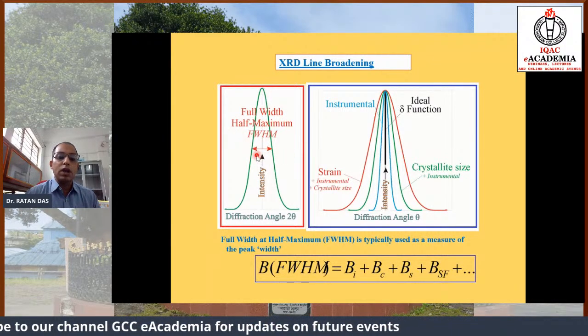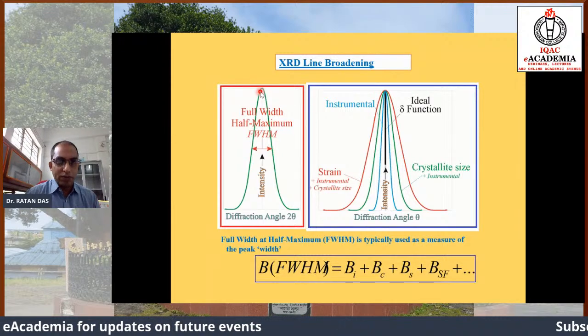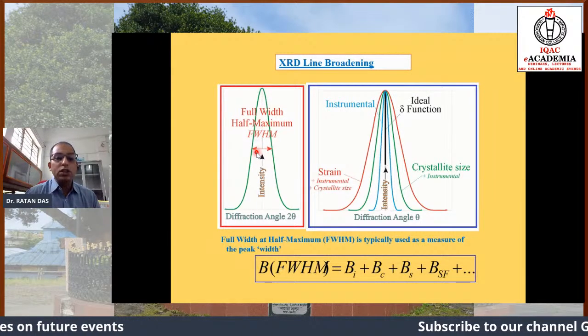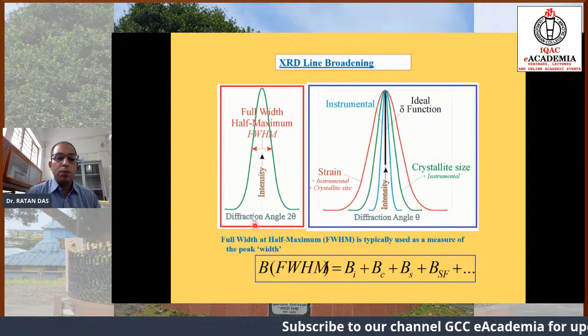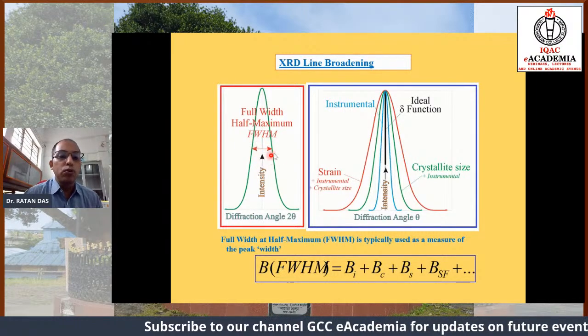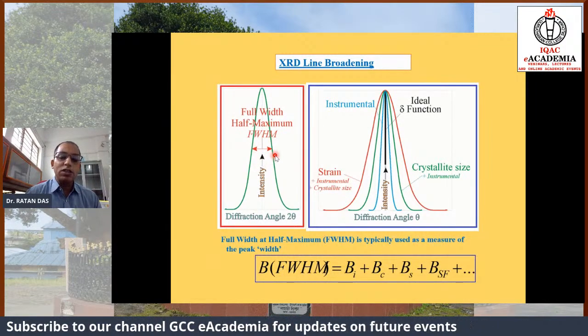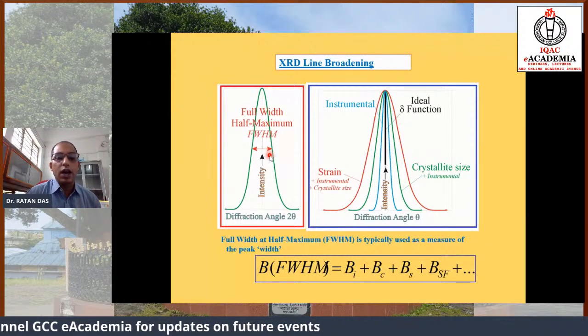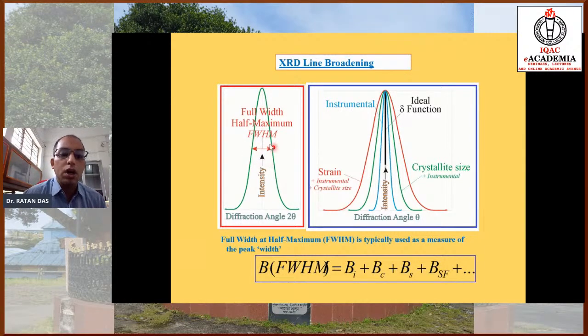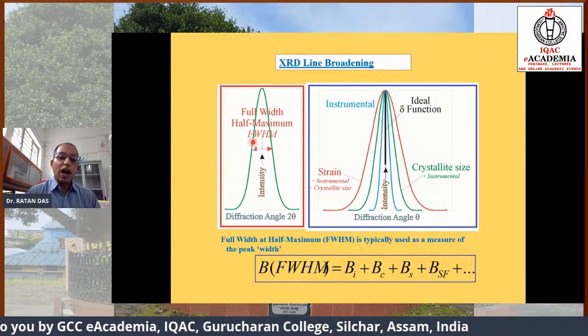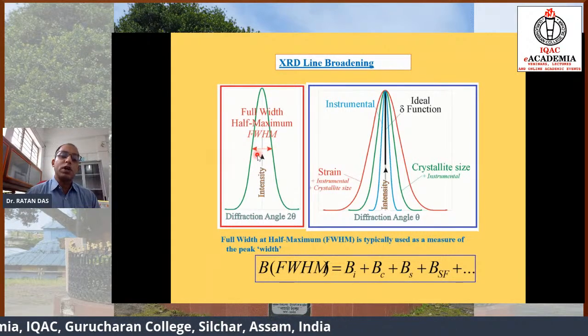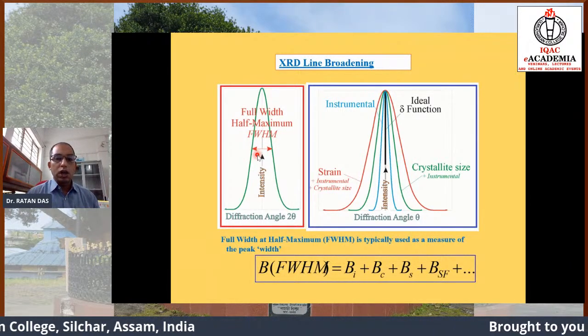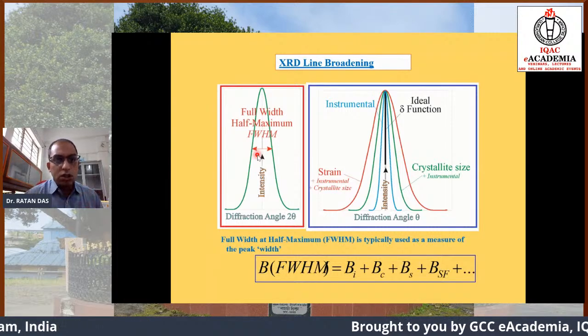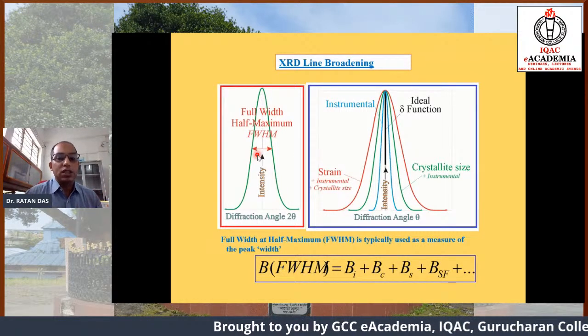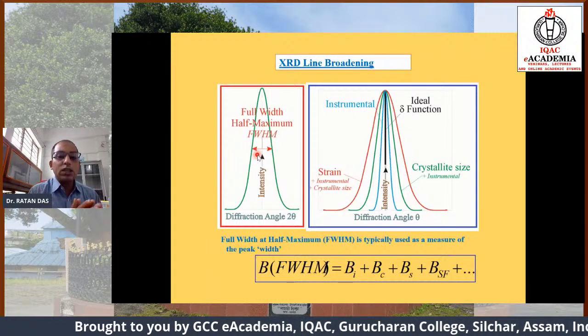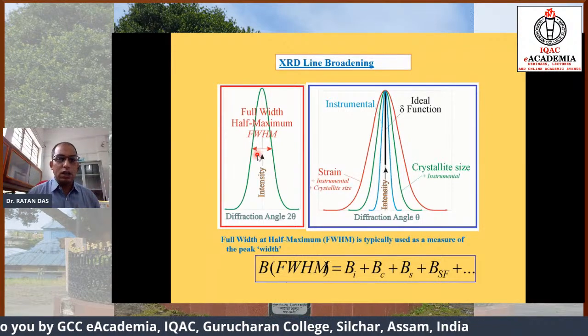At the half maximum, I mean half of the intensity of the diffraction pattern, the full width is beta actually. So that beta is nothing but full width at half maxima, and the size of the nanocrystals or crystalline size is inversely proportional to the full width at half maxima. If the width is more, the smaller is the size, and the smaller is the width, the higher is the size.